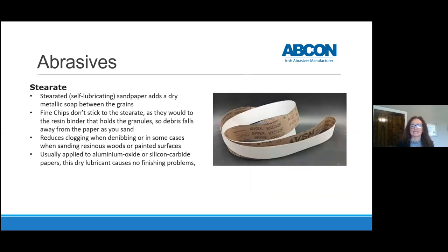So stearate is a self-lubricating sandpaper. Basically a dry metallic soap lies between the grains, which means that fine chips don't stick to the stearate as they would to a resin binder which holds the granules. So debris falls away from the paper as you sand. It reduces clogging when denibbing, or in some cases when sanding resinous woods or painted surfaces. So this would usually be applied to aluminium oxide or silicon carbide papers, and it's a dry lubricant, so it causes no finishing problems.